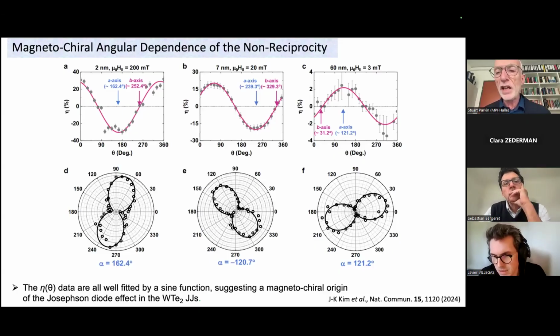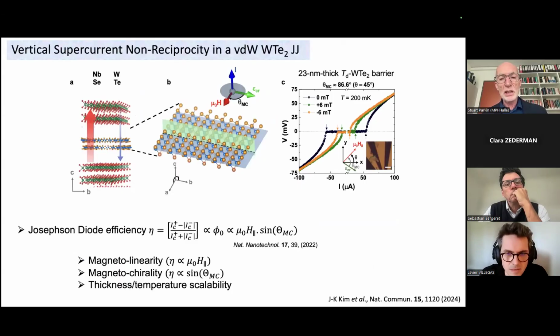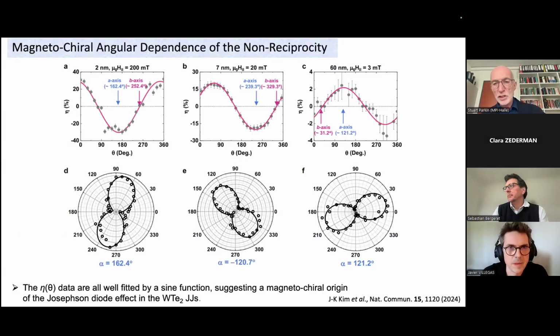And in each case, we find that the maximum diode effect is when the field is applied along the A-axis, and that axis is perpendicular to this mirror plane. So in every single case, all these junctions, we don't know the crystal orientation of the tungsten ditelluride, but after we've determined it, we find that the maximum diode effect is always when the field is oriented perpendicular to the vertical current, but is aligned in a direction perpendicular to that mirror plane. So we've correlated the Josephson diode effect with the crystal lattice of the tungsten ditelluride.